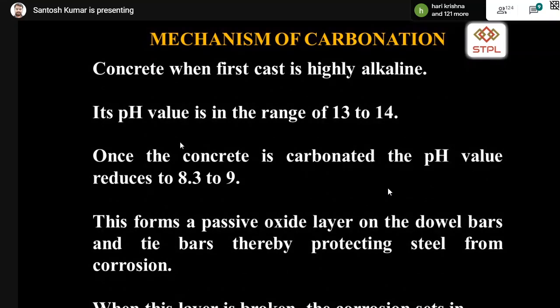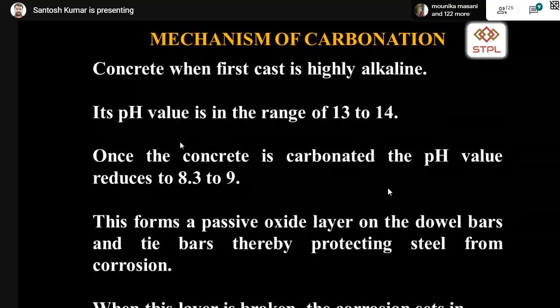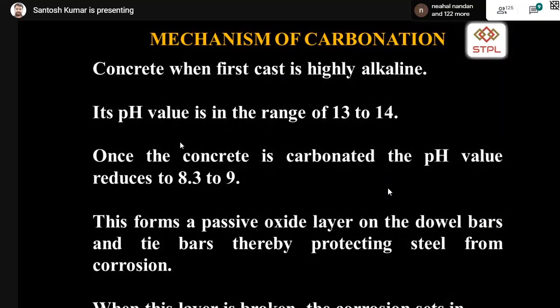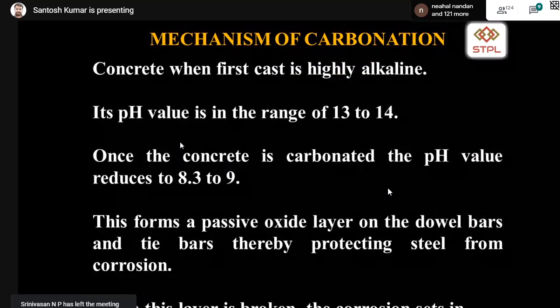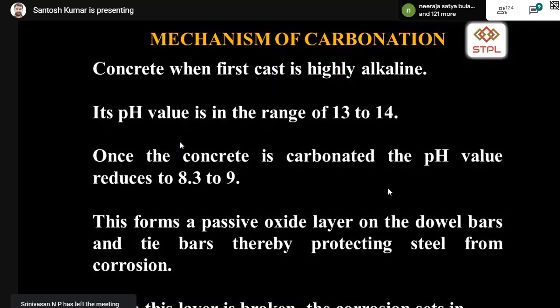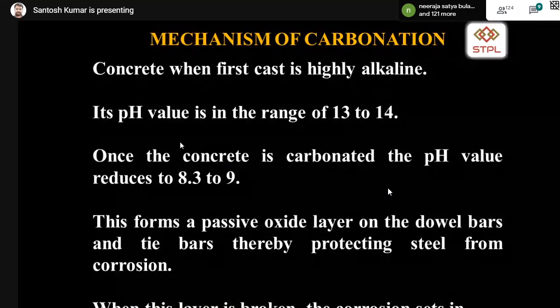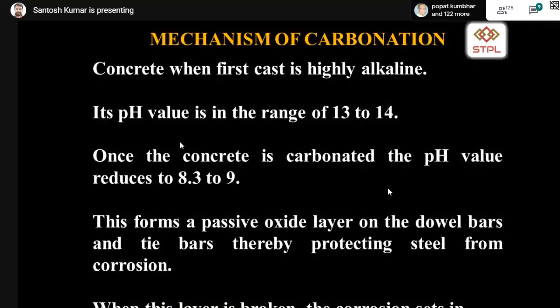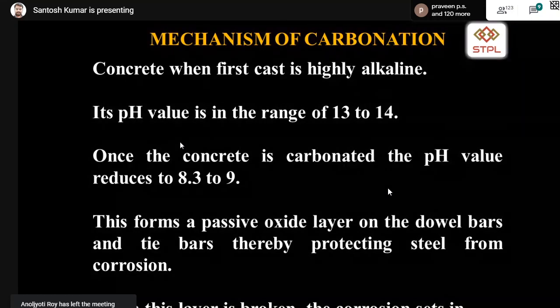Concrete, when it is firstly cast, it is highly alkaline. The pH value of concrete will be 13 to 14 for a freshly laid or freshly hardened concrete, I can say. But once the concrete is carbonated, the pH value comes down to 8.3 to 9. Your pH value is down means your concrete is not alkaline, and because of this carbonation, let me tell you one thing clear, sir. The absolute volume of concrete will be the same, but inside the concrete, the pores will increase because of the carbonation. The calcium hydroxide in your concrete creates pores when this concrete is carbonated.